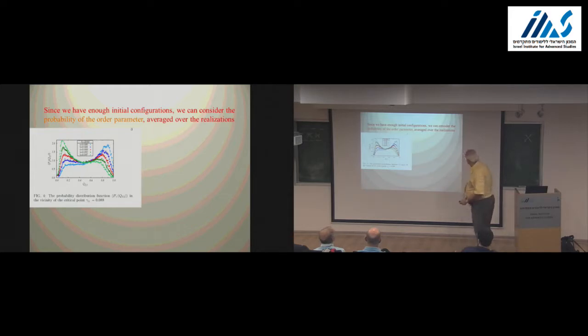So you see, if instead of a PDF I ask what is the effective free energy that is associated with this, well, it's a double well when I have the two peaks more or less the same, like here in the red line. But then there will be some point where this is going to flatten. When it gets flattened, this is the spinodal point. You are getting only one phase stable. The other one has no stability at all.